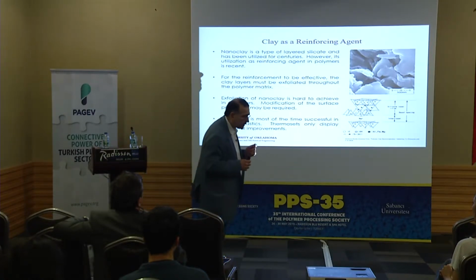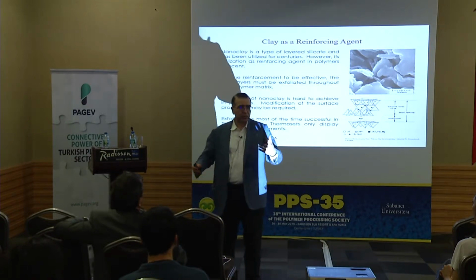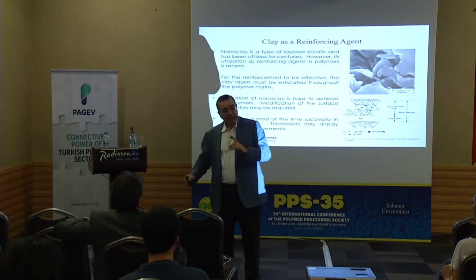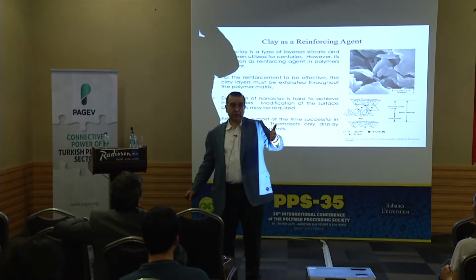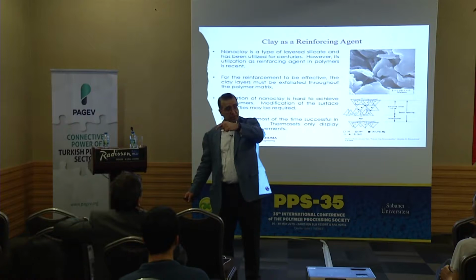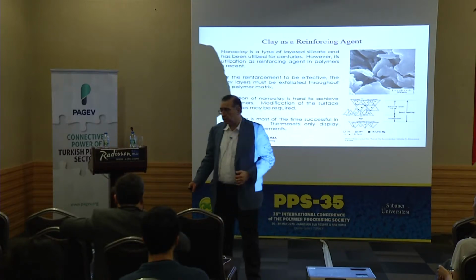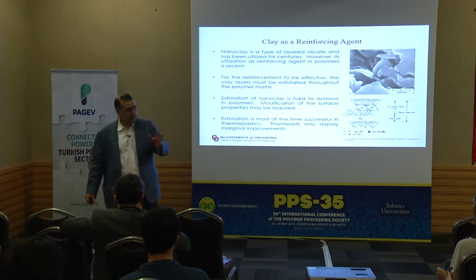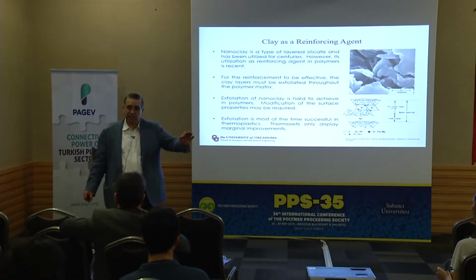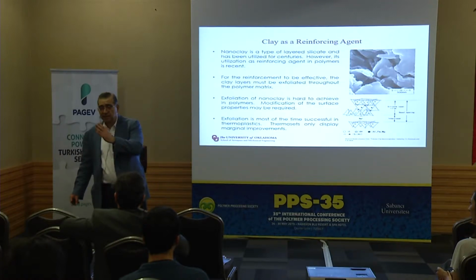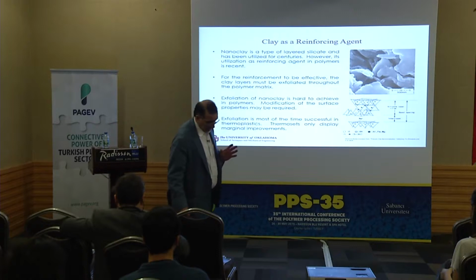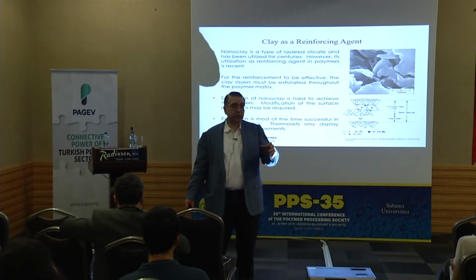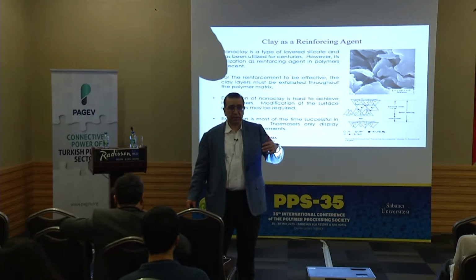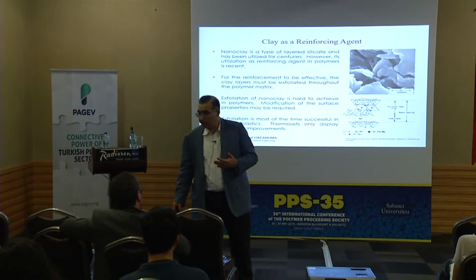The appeal of clay is that it's cheap, right? So you can get clay and you may use a small amount of clay. Now, for fibers, you really need to use at least 20% by volume, and for high performance applications, 65% by volume in the laminate fiber side. Clay, you can use 2%, 3%, 5%, and people primarily stayed in that range. People didn't really exceed 5% clay. There are a lot of studies claiming successful integration of clay and improving properties with 1.5% clay, 2% clay.